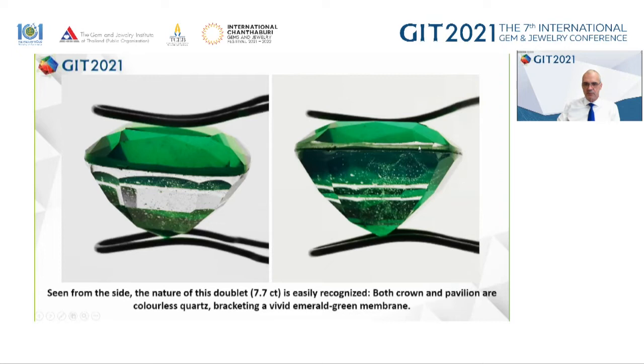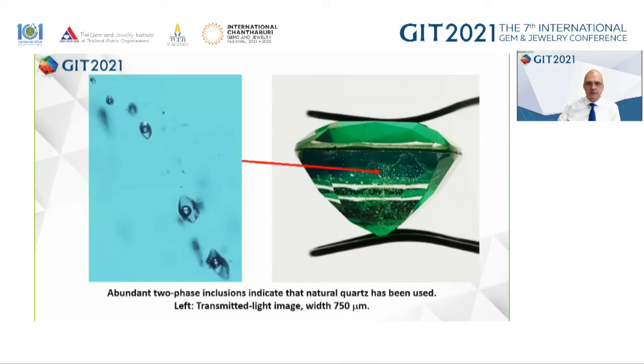Here on the upper right it can be seen quite well, and it's remarkable that this material here is quartz, it's not glass, and it is a quartz that is fairly rich in inclusions. So given the average quality of synthetic quartz, it appears quite likely that this is here some natural quartz rock crystal that has been used to produce these doublets.